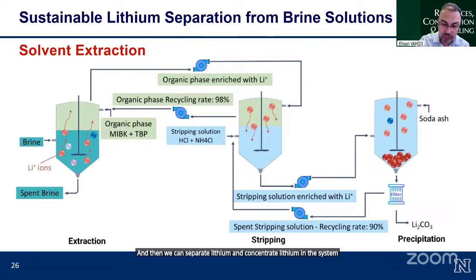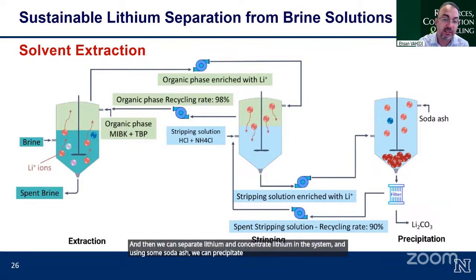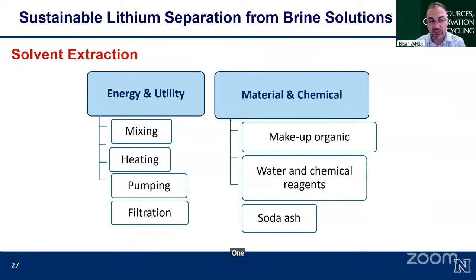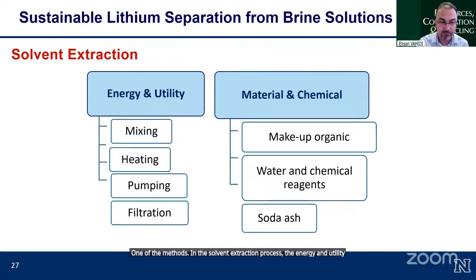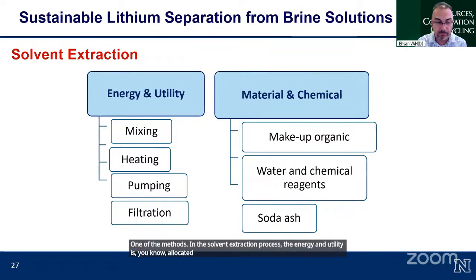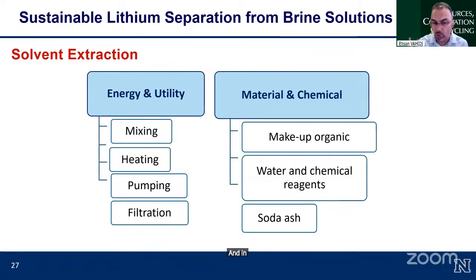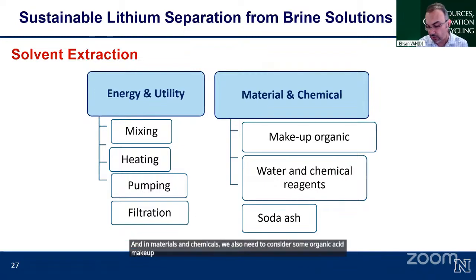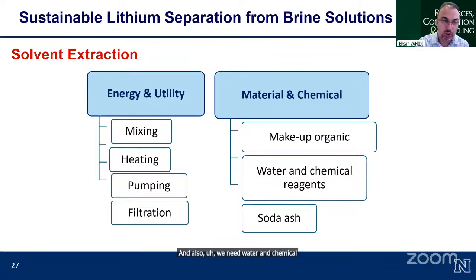And using some soda ash, we can precipitate lithium carbonate equivalent. This is one of the methods. In the solvent extraction process, the energy and utility is allocated to mixing, heating, pumping, and filtration. And in materials and chemicals, we also need to consider some organic acid makeup, because in solvent extraction we always lose a little bit of organic acid, and we need to add fresh organic acid. Also, we need water and chemical reagent, and soda ash.